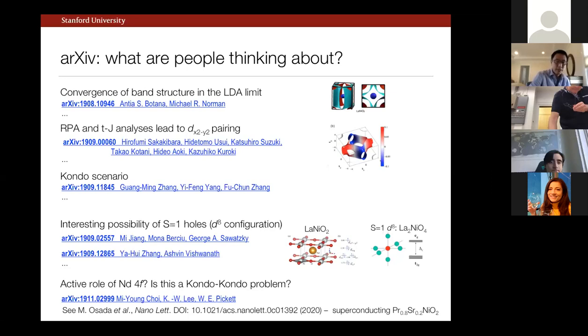I would certainly also mention that indeed that's what's found in the two-dimensional layered nickelate version of D8 configuration. So namely La2NiO4. So this is very much the same structure as the 214 cuprates. In this system, when you hole dope, let's say strontium into the lanthanum site, indeed what you find is the high spin configuration.